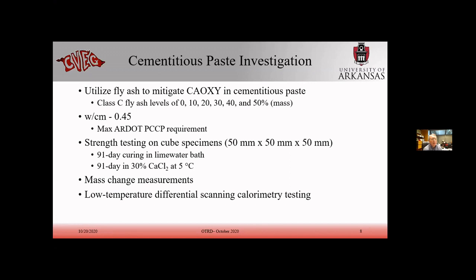We made cubes, 50 by 50 millimeter cubes. They were stored 91 days in a lime water bath, and then an additional 91 days in a 30% calcium chloride solution at 5 degrees C. The 30% calcium chloride solution is what has typically been used in previous research, so we kind of piggybacked on that. We looked at mass change, and then we looked at the LTDSC, the low temperature differential scanning calorimeter. Dr. Royce at Oregon State has one of those. We don't at Fayetteville, so we send a lot of our samples off to him, and also to the CP Tech Center.